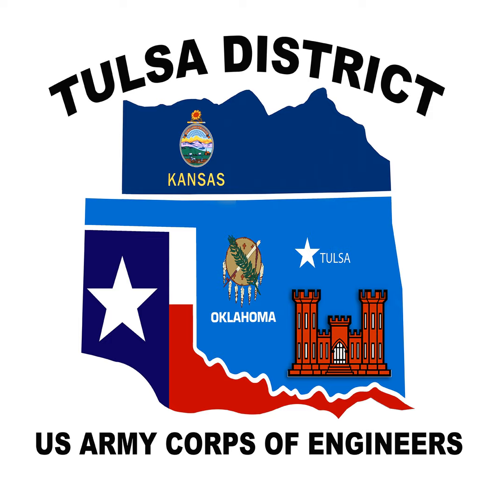We looked at several different possible uses of UHPC, both the stuff you can buy from the manufacturers as well as locally developed materials. We did bridge deck joints that are similar to the ones on the Eufaula Bridge, but they're intended to be expansion joints. And actually, the Eufaula Bridge is going to have some UHPC at the expansion joints, very similar to what we were doing with ODOT.